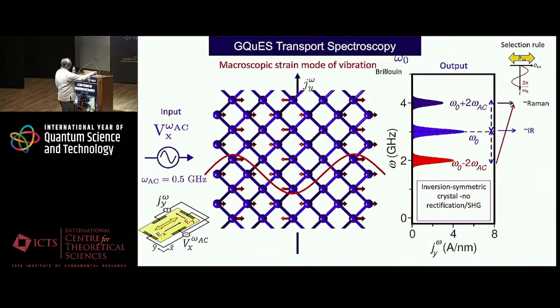Transport meaning you just have a simple 4 electrode device like this, apply an electric field with a frequency omega, and measure a Hall current as a function of frequency. You will see there are 3 peaks we predict using this spectroscopy. One is associated with the vibrational mode, which is like an IR active mode. And this is, by the way, when you have no Berry curvature dipole to start with in the system. So the equilibrium symmetry of the lattice is not so crucial to this.